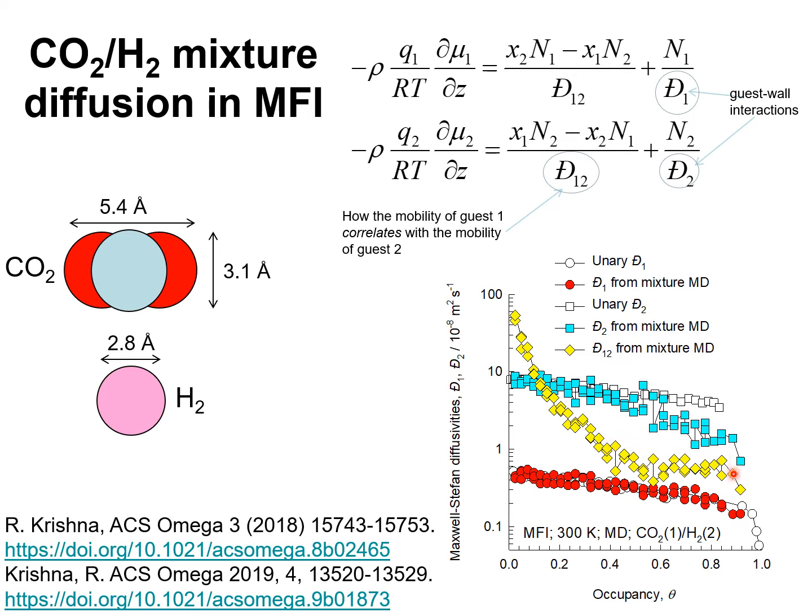And as pore saturation is reached, the D12 term is lower than the Maxwell Stefan diffusivity of hydrogen, but higher than the Maxwell Stefan diffusivity of CO2.